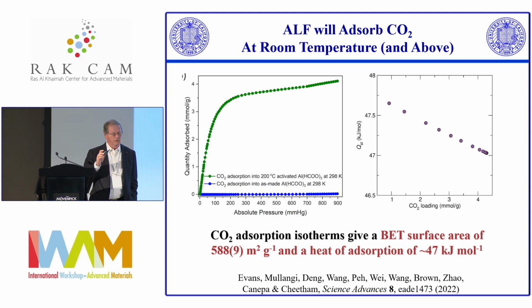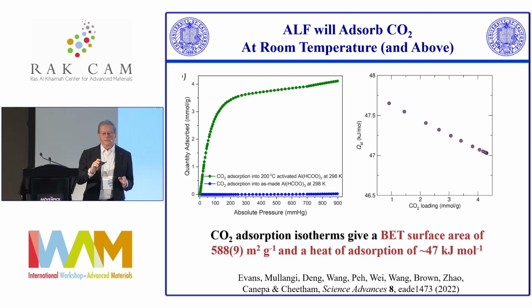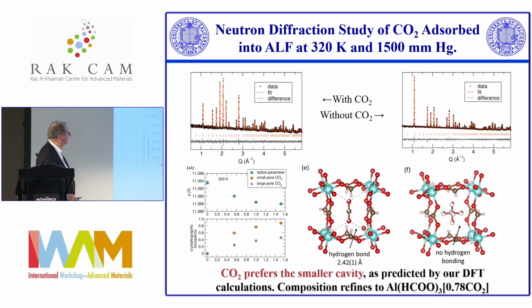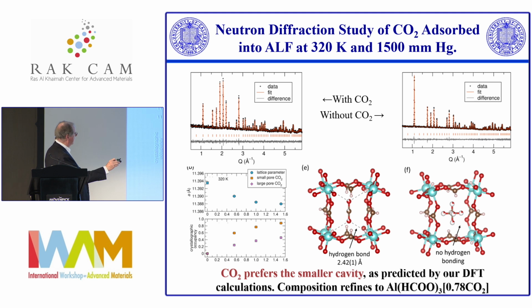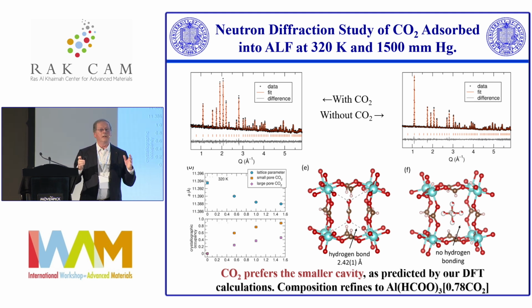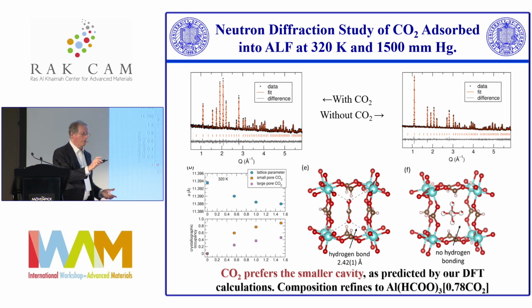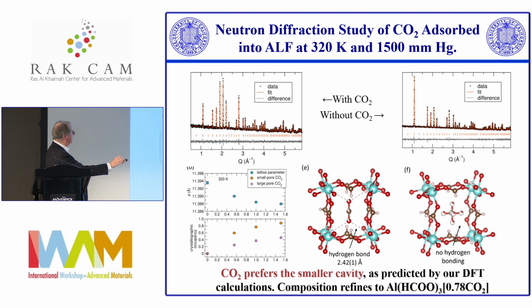We then turned our attention to the CO2 loaded material, and we did a whole series of neutron diffraction experiments at NIST. This is the neutron diffraction pattern that we just looked at of the pristine ALF, and this is with CO2 in the cavities. We did this as a function of loading and a function of temperature, so we got a lot of data on this. And we know that the CO2 goes into the small cavity and hydrogen bonds, and it's locked into a single position. So that's 3/4 of the cavities that are nearly full.